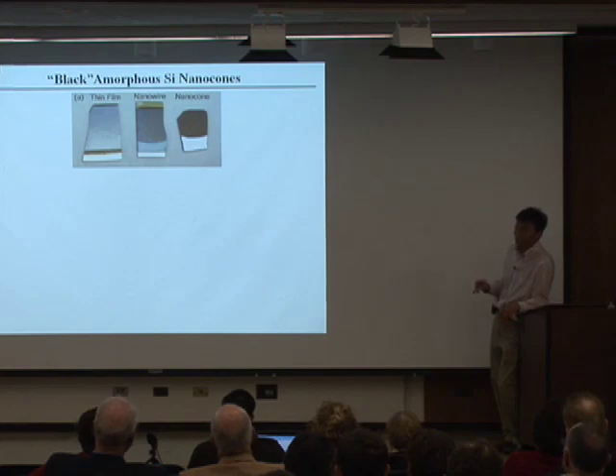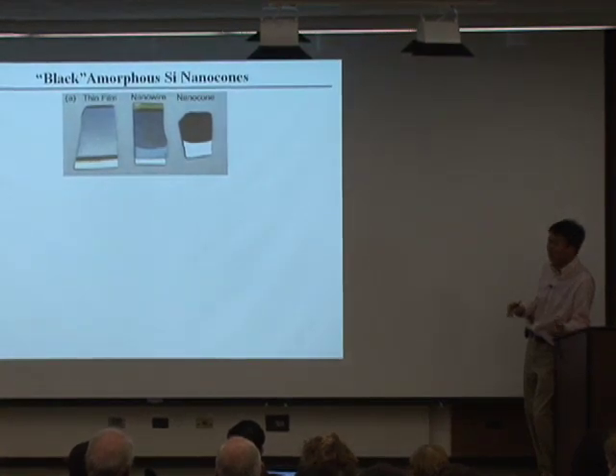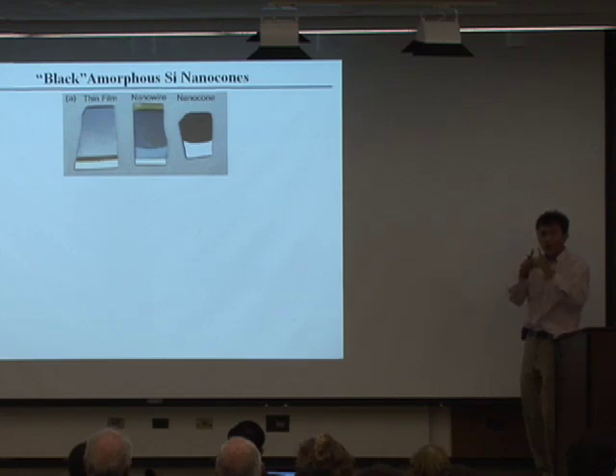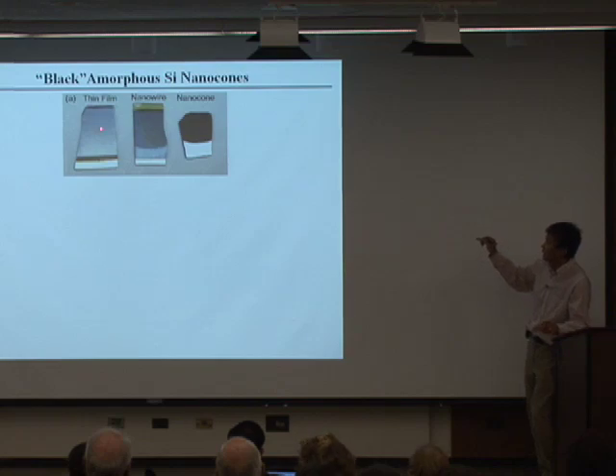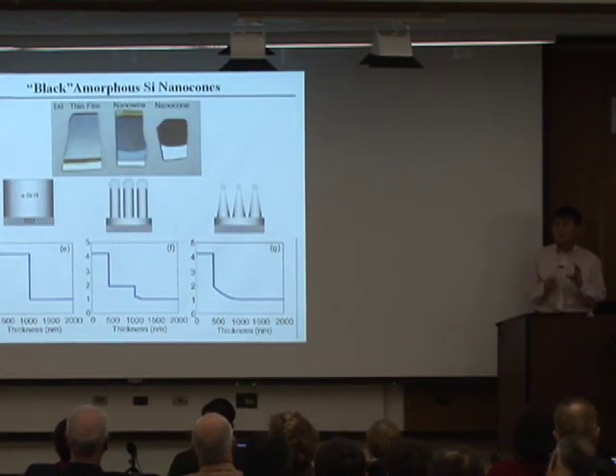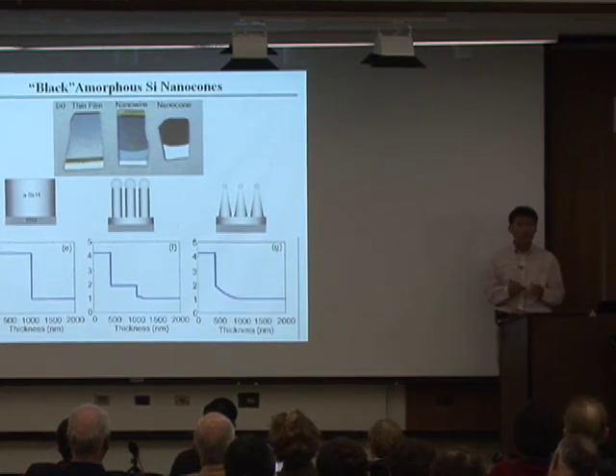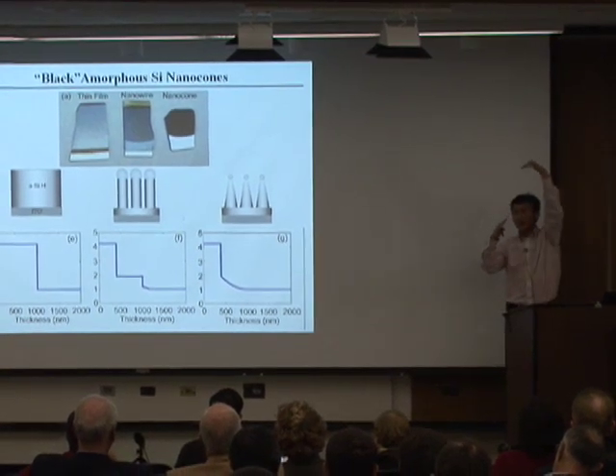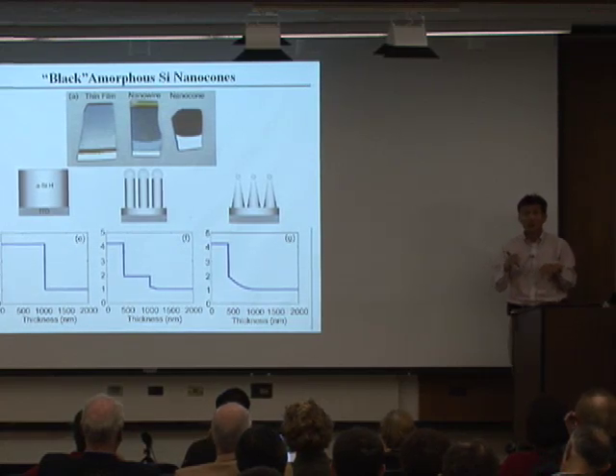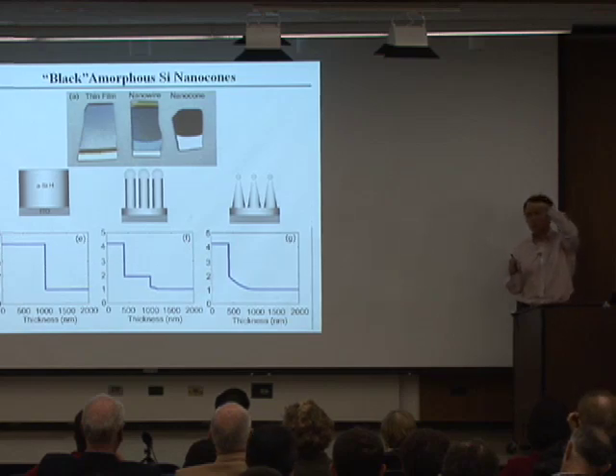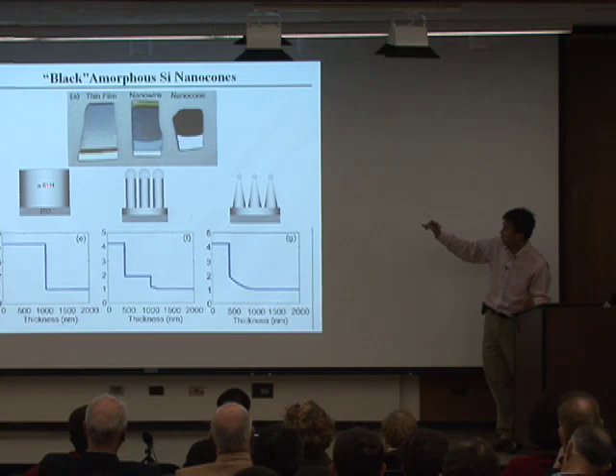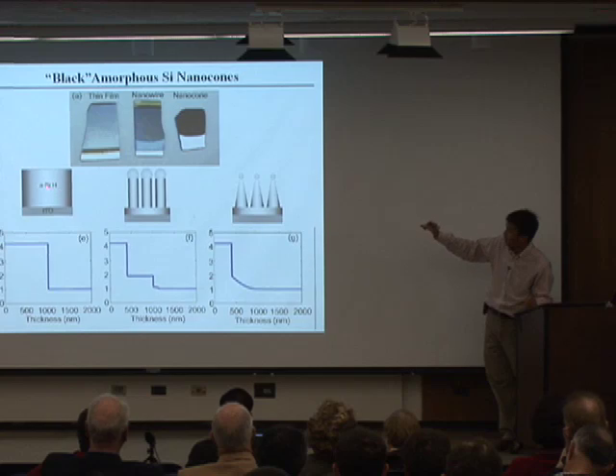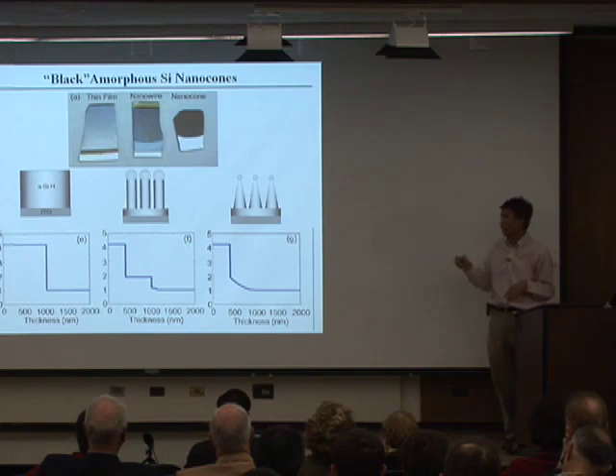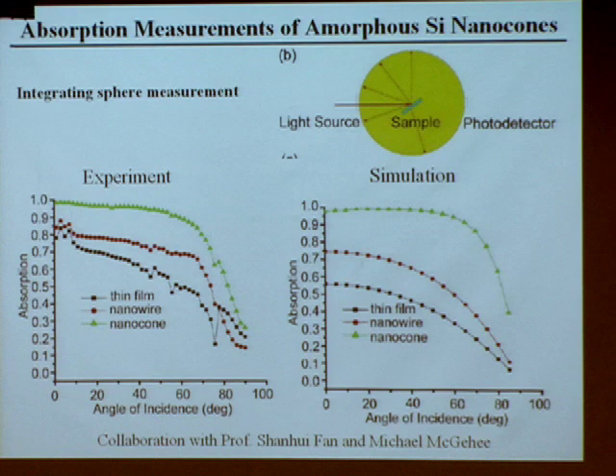This is a nano cone. They look black. You would like your solar cell to look black. They don't reflect light. They absorb all the light. And this is just a vertical pillar, no cone shape, just vertical. They are gray. If it's a film of the same thickness, it looks only gray. So this is very good for solar cells. The reason they reflect so little light is the so-called refractive index matching. Having the cone right there, light comes in and sees the tip of the cone and goes into your cone-shaped structure. And the refractive index gradually changes from air to your amorphous silicon. It's not like a step function change if light comes into an amorphous silicon film. Refractive index right here is 1, right here is 4. So it's a dramatic change, and light gets refracted back. But in this case, light just can get completely trapped in and get absorbed. So we have done very detailed measurement. This is collaboration with Shanhui Fan and Michael McGehee.